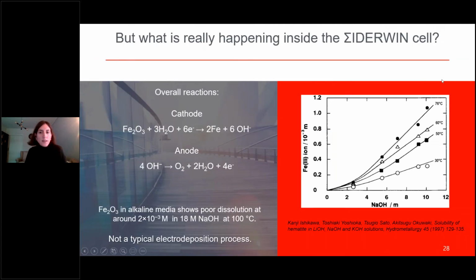The overall reactions that take place during electrolysis of iron oxide are the iron oxide reduction and the oxygen evolution, but the system seems to be more complex than that. The hematite dissolution in alkaline media, shown in the diagram on the right, is quite low. More specifically, for 18 molar sodium hydroxide at 100 Celsius degrees, it was found that around 2 ppm of iron is dissolved in the solution.